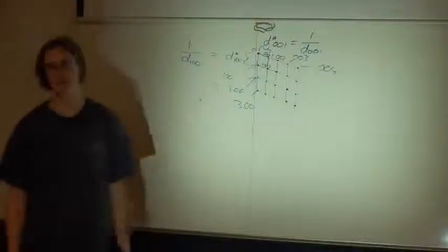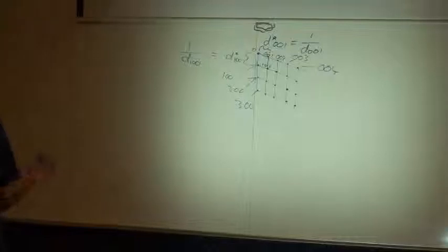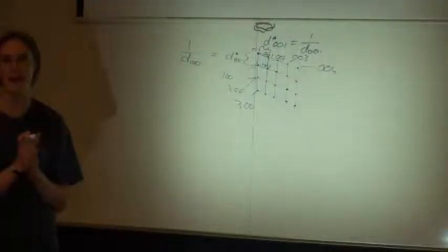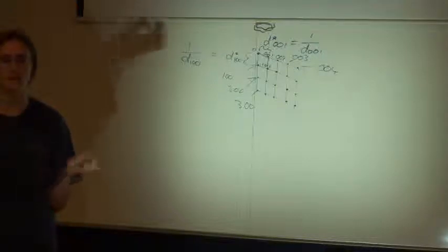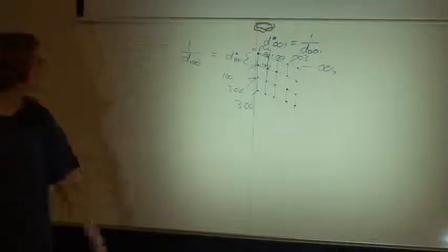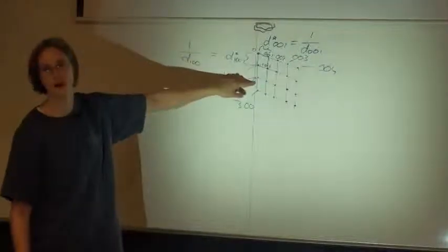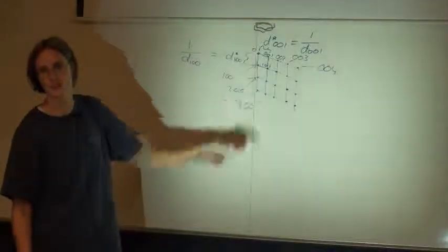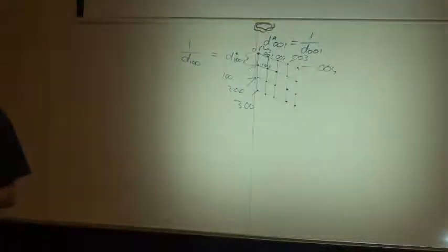Because it's reciprocal, right? Our 200 family of planes in crystal space would cut at a half unit cell. Well, that means we all of a sudden double the distance, right? So our distance from the origin has to be twice as far for that one. So in reciprocal space, all of a sudden all of our counting works nicely again.